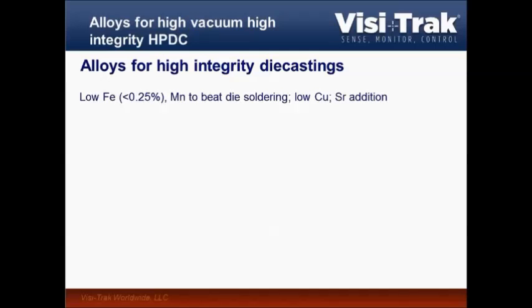All these high-integrity die casting alloys have a few things in common. One of them, they're all low in iron, and I'll show you a few pictures later on what iron actually does. It creates big platelets that destroy our properties. So typically these alloys replace iron, which is used for beating die soldering, with manganese, which does the same job without damaging our properties so much.